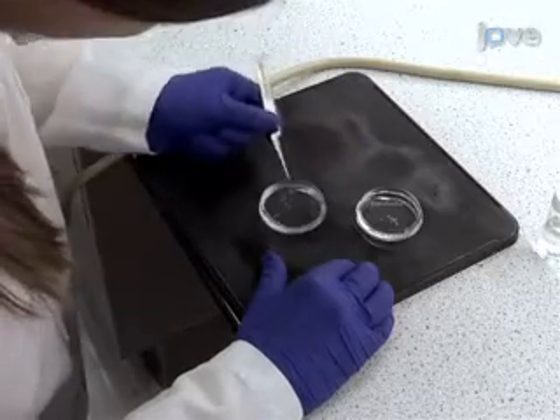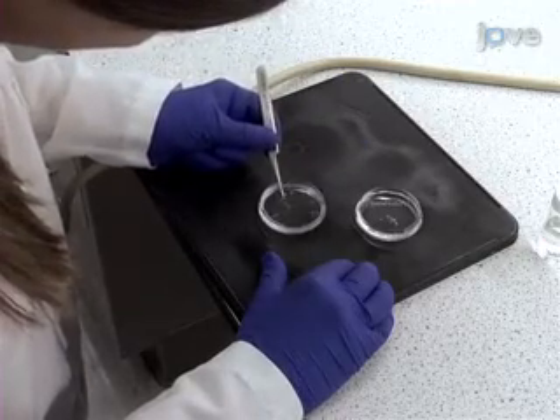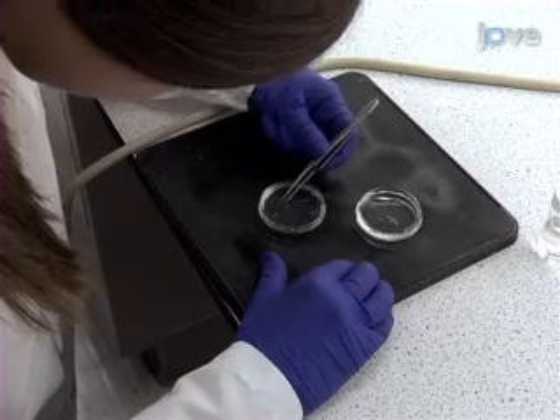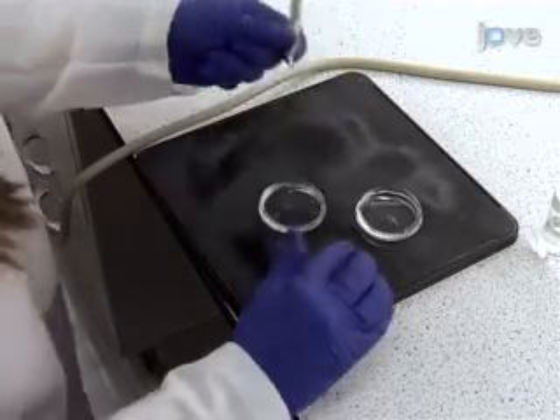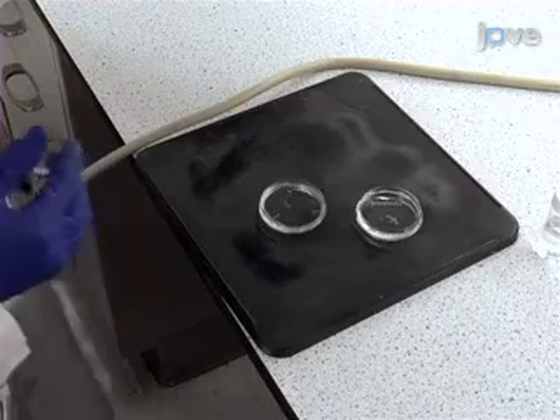The control comparison begins by immersing the setup samples for at least 30 minutes in phosphate buffered saline, or PBS, to allow it to soften to its minimum Young's modulus.